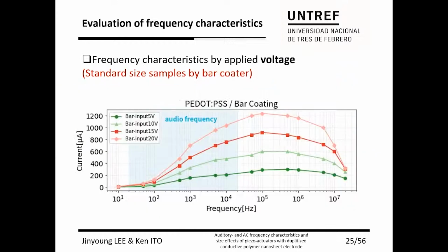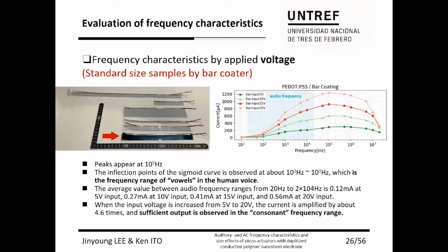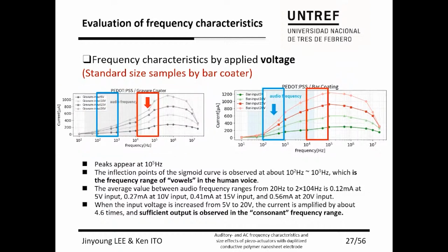Next, this is the characteristic of the standard size sample made by bar coater. The inflection point of the sigmoid curve is observed from 100 to 1000 Hz. Let's compare with the micro gravure coater sample. The inflection point of the bar coater sample has moved into the low frequency region of the audio range. This result shows that the bar coater sample has higher output in the consonant frequency range.